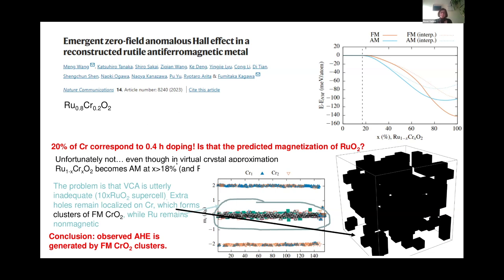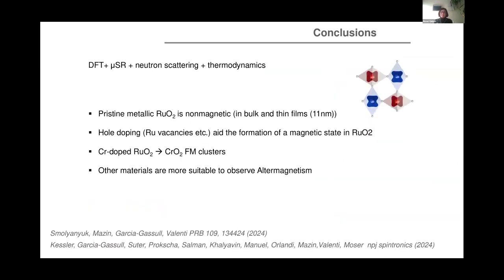So this is telling us that ruthenium dioxide is probably not the best system to look for altermagnetism. We have seen that there are other materials that are really beautiful, that show this altermagnetic ordering and all these features that we have been seeing in the previous talks. But ruthenium dioxide is not a good one, because what all these calculations, as well as mu-SR, neutron scattering, and thermodynamic measurements show is that whether you find altermagnetism or not is rather sample dependent. And even in the chromium-doped case, this type of doping builds these chromium dioxide ferromagnetic clusters, and you don't see this altermagnetic ordering. So with that, I come to my end.